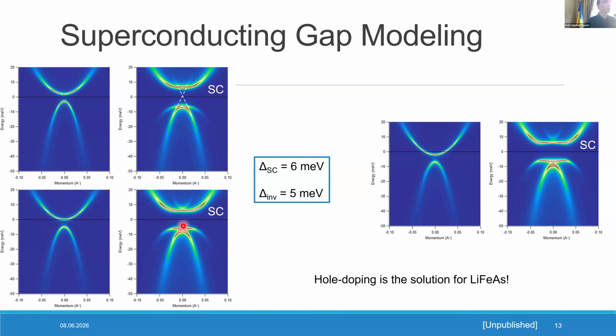So this is the case of superconductivity and topology basically competing, and this interplay plays an important role in this material. In the case when this band is even deeper, it gets even worse. Again, this is for the case of a 5 meV inverted gap. If the gap is smaller, the effect is even stronger. That's why the ideal solution for how to proceed is to dope the material with holes, which will move this up. This band should move higher, and therefore the inverted gap should move higher. And ideally we want, of course, this case, or at least this case.